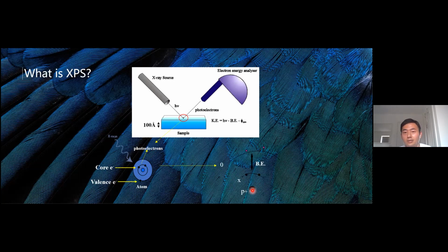If we look at those electrons in the core orbital, after they escape from the atoms, they have certain kinetic energies. With this equation, we know the kinetic energies of the photoelectrons and the X-ray source energy, and we'll be able to calculate the binding energy of the photoelectrons, therefore identifying the elements.